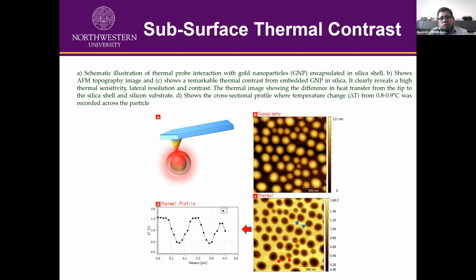This is another example where we use gold nanoparticles within silica structures. The idea is to see whether we can get thermal contrast from the gold nanoparticles. In thermal imaging, conducting particles or regions draw more heat from the probe, so you can map thermal conductivity as well as temperature. The dark contrast in the image indicates a more conducting area because it draws more heat from the probe. We are heating the probe with a laser to around 40 to 42 degrees. In the bottom image you can see the contrast from those gold nanoparticles, and in the topography you don't see anything. So you can see thermal contrast from embedded structures.